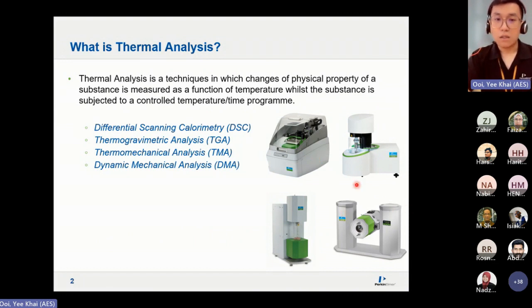So DMA 8000 measures the viscoelastic properties of the material. A good material to study using DMA will be your rubbers, meaning your elastomers. It measures how much or which part of the material is actually viscous, and which part of it is actually the elastic. So you can get the information. Usually people use it to represent Tg as well, because Tg is a weak signal. You might not see it under DSC.